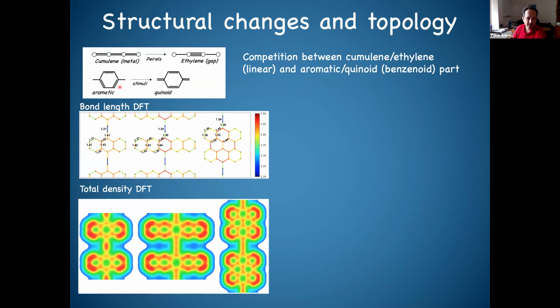And again, what we claim is that we now have one system which is topologically trivial and the other system which is topologically non-trivial. But now the question is, what is the relation between topology and pi-conjugation? Indeed, from the DFT calculation, I already mentioned, we can have a look directly at the bond. We can see that there is a substantial change when we go from anthracene to pentacene. We can also see it in the electronic density. I do a cut of the electron density, and when I see the triple bond, I get more accumulation of electron density, because the system tends to localize 3 bonds virtually, unlike the other system, pentacene, where you will see that this triple bond disappears.